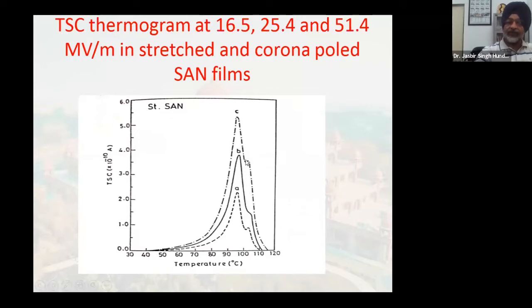So that corresponded basically to the glass transition temperature, and this corresponded to the temperature at which the maximum polarization had been obtained, and that temperature had to be kept, right? So this is at the different poling fields we did. Okay, that was for thermally stimulated current studies.